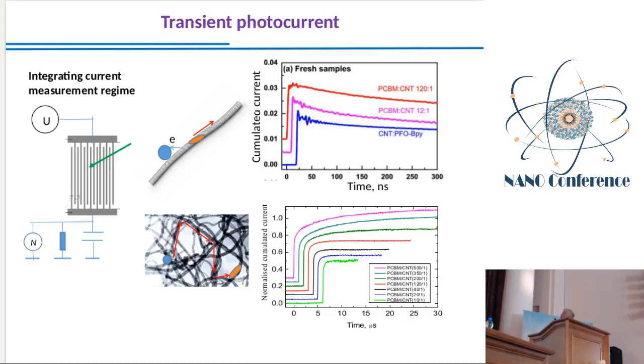Here we investigated transient photocurrent. We excited our sample and looked at the photocurrent. Using a 50 ohm load, the photocurrent is relatively low, therefore we used an integrating photocurrent measurement regime. So current passed like this, and it was integrated on this integrating capacitor. Therefore, our current is just a derivative of these curves, and later on is the charging of our capacitor.